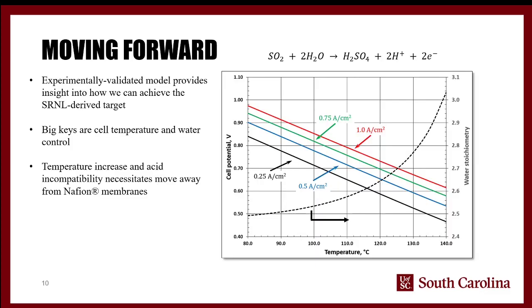And going back to this figure, that's what this assumes. This assumes that we're using the SPBI membrane. We've started working on it, and it is better. You don't have to flow any water at all to the cathode. You can very carefully control the water on the anode, which means you have much better control over the acid concentration coming out in the product stream. And most importantly, it removes one of the major issues that you have to deal with when you work with Nafion, which is water management. You don't have to do water management outside of controlling what you need for your reaction on the anode.